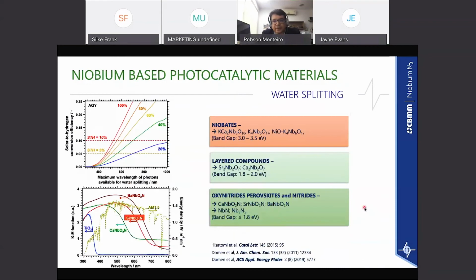When it comes to niobium, it is very interesting how niobium can help to make better water splitting photocatalytic materials. If you look at this graph here on your left-hand side, this is what we call solar-to-hydrogen efficiency, as opposed to the wavelength of the sunlight that reaches the Earth. So you have lines we call quantum efficiency. A good photocatalytic material needs to have a very good solar-to-hydrogen efficiency: how many photons you can use, the energy of these photons that come from the sunlight, in order to really transform into hydrogen. And you need to do that as efficiently as possible.